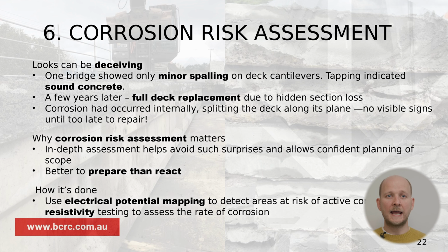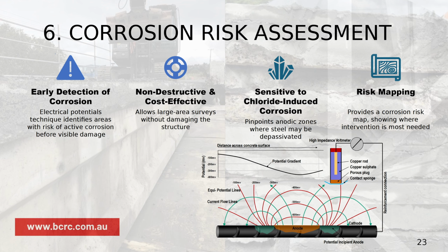It's important to say, though, that it does detect a risk of active corrosion. It does not confirm corrosion. And it's often used with a resistivity testing, which I mentioned earlier, which also helps to assess the rate of corrosion. This test is non-destructive and very cost-effective. Some of the modifications of this equipment actually allow to scan very large areas fairly quickly. Although you do need to drill a few little holes to connect to the reinforcement, but these holes could be repaired quickly. It's quite sensitive to chloride-induced corrosion, which is what we need.